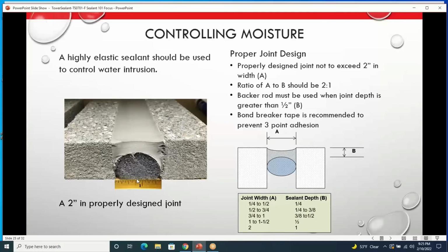If the sealant were to go all the way down to maybe where the joint ended, that gives you 3-point adhesion. That puts additional stress that actually contributes to a proper joint failing sooner. So not only does your applicator save a boatload of money by filling gaps like this with backer rod that comes in various sizes, it actually gives you a better joint by having strictly 2-point adhesion and not 3. So this is what you would want when you're specifying a building and what we typically see in drawings and plans. The drawing here to the right is just an example of it. Again, a properly designed joint.